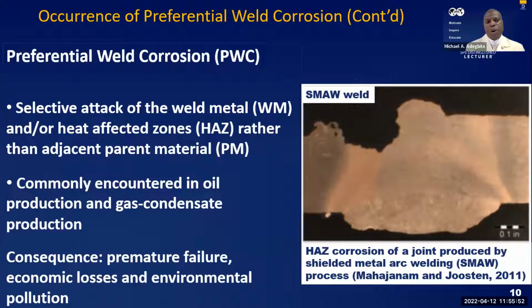Here is an incident. When we say preferential weld corrosion, we are considering selective attack of the weld metal or selective attack of the heat affected zone, or perhaps both. So it could be the weld metal and/or the heat affected zone selectively corroding, going into solution rather than the parent metal or the base metal. So when the base metal being joined is more noble or will not corrode as fast as the weld metal, or as fast as the heat affected zone, or the two of them combined, then we have what we refer to as preferential weld corrosion.